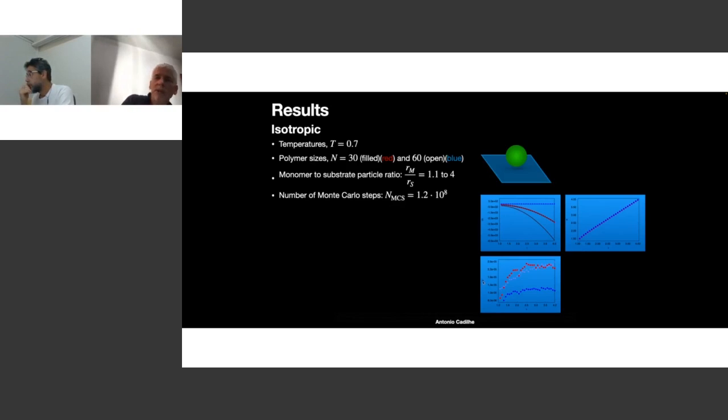For example, if I calculate the diffusion coefficient, then for small sizes the diffusion coefficient grows rapidly for the smallest polymers, but for the largest ones, it also grows initially, but not in the same way, which is, it's a larger polymer, so it's slower, it has a smaller diffusion coefficient, and it gets basically saturated not long after as the sizes of the monomers increase.